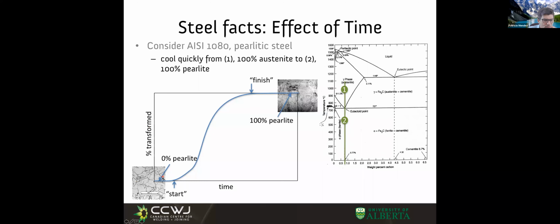So this means 100% austenite at the very beginning, the instant I quench. And then I wait. What do I see? If I wait long enough, I'm going to have 100% pearlite, that I know. At intermediate times, we see - and people measure this in the lab with machines - how we go from 0% transformation, and the transformation gets faster and faster. Then as it reaches completion, it slows and becomes asymptotic towards the top.